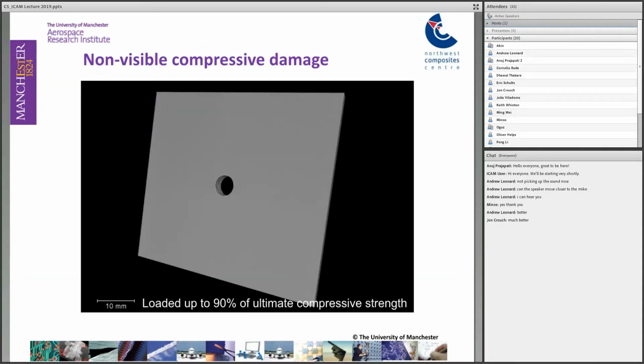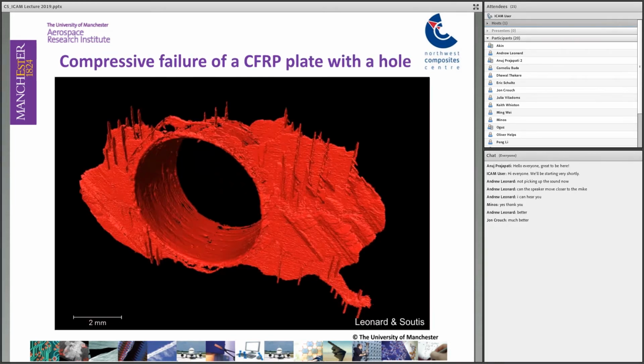And then on this one, we look at this internal damage, which is non-visible damage. In this particular case, we have a multi-layered carbon fiber plate with an open hole, which has been loaded to 90% of its ultimate static compressive strength, and there is no visible damage. So we're not aware if there is any damage inside this construction. And the only way we can observe this is by using X-ray CT, computed tomography, where we can see some actual cracks growing by the edge of the hole, some off-axis matrix cracking in the plus and minus 45 layers, and extensive delamination between those plies.